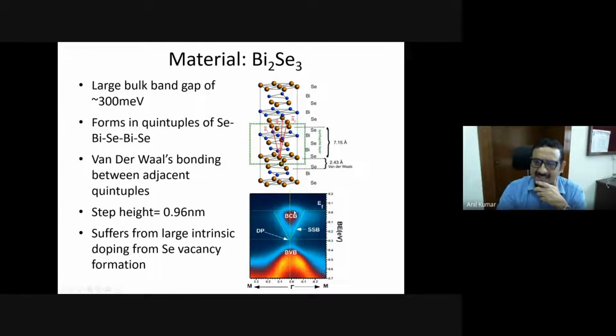Now, this is the band structure which I showed you earlier. If you look at the Fermi level of this material, the Fermi level is in the bulk conduction band. What does this mean? Ideally, I wanted to have the Fermi level in the band gap. Now the Fermi level is in the bulk conduction band. That means, though I said this is an insulating material covered with a surface state, my insulating material is also becoming conducting because my Fermi level is lying in the conduction band.